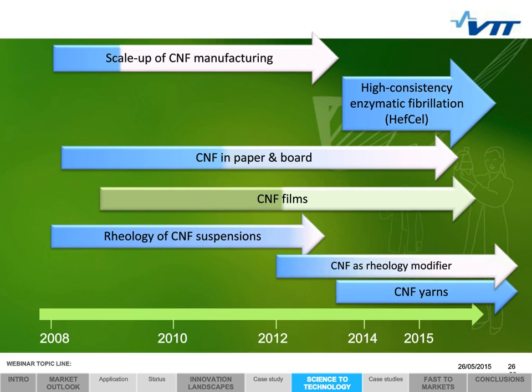Next, I will present some research examples on cellulose nanofibril films. Cellulose nanomaterials have an inherent tendency to form films upon drying. CNF films as such have been found to be very good oxygen barriers. However, as hydrophilic, meaning water-loving materials, they are sensitive towards moisture and water, which naturally limits their applicability, for example, as packaging materials. At VTT, we have taken different approaches to tackle the challenge of moisture sensitivity of CNF-containing films.